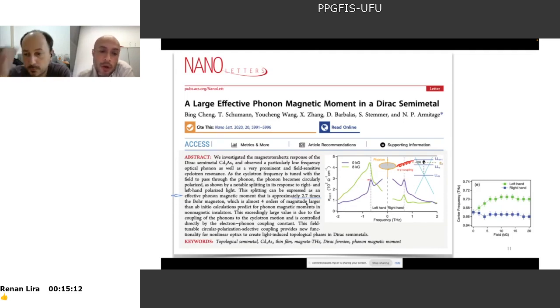And they say that when you have this crossing between cyclotron resonance of carriers and phonon resonance, then you have an enhancement of the phonon magnetic moment, given this large effective result. Here I put the most important result of this paper. This is the frequency of the phonon, and then you increase the magnetic field. And when you have the crossing between the cyclotron resonance and the phonon mode, then at a given field, you have this enhancement.